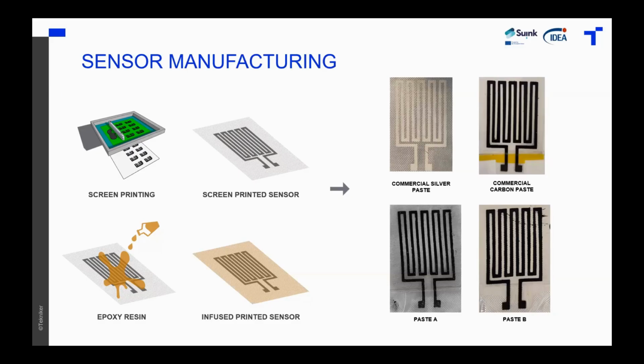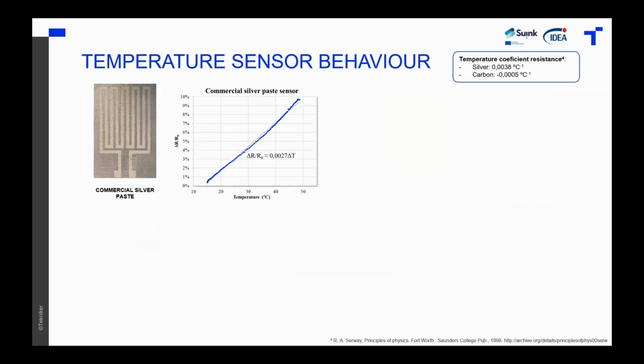After this, we characterize them in a climatic chamber, which modifies the temperature with a constant humidity, and we represent the variation of resistance with the temperature variation. For the commercial silver-based sensor, we could see that we have a linear tendency, and we can say that the temperature coefficient of resistance that we are obtaining is similar to the one that we can find in literature.